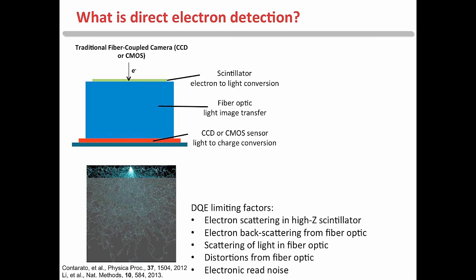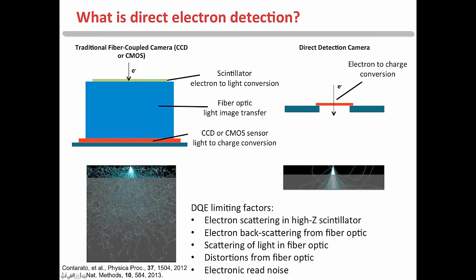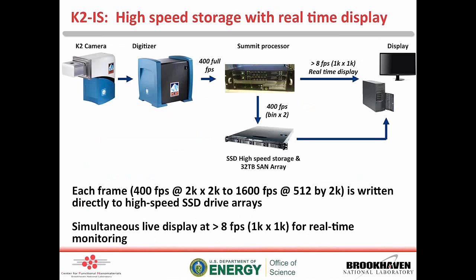And so the direct electron idea, it's been around for a while, but there was really a major advance made as part of the DOE's TEAM project. This paper down here is probably the best one to point that out, and it was commercialized by Gatan here. The idea there is that you basically use a camera that allows you to directly convert the electron into a charge. You back thin it. This allows you to have less scattering within the camera itself. And you end up getting quite a number of additional advances. There's limited scattering in the low Z silicon sensor. You remove all the fiber optic problems. You still have read noise, but it's less so.